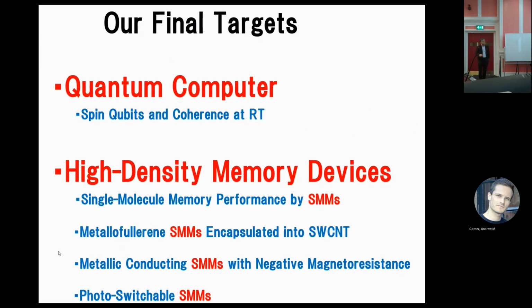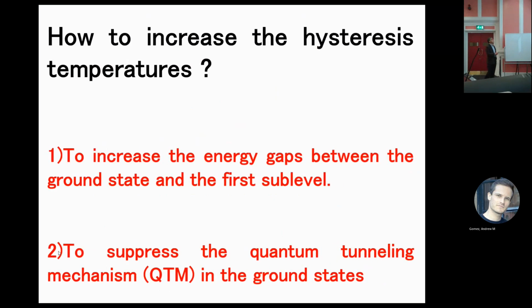So as I told you, every time we use a single-molecule magnet to overcome Moore's limitation. But the important thing is how to increase the hysteresis temperature. Now, the highest hysteresis temperature is 80 Kelvin. Richard Layfield at Sussex University has a champion record, 80 Kelvin. But we must increase the hysteresis temperature to around room temperature.